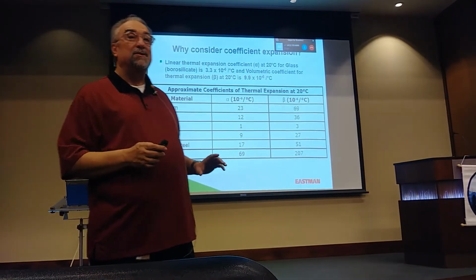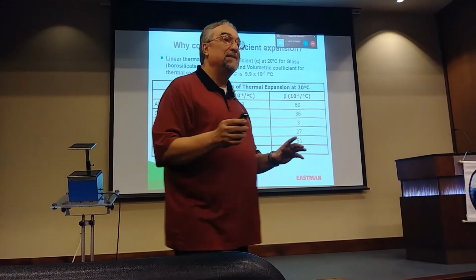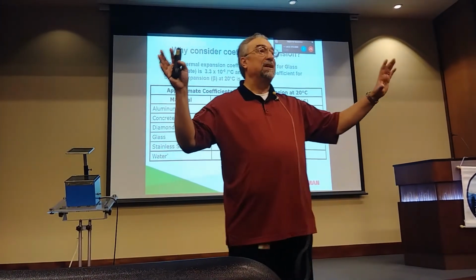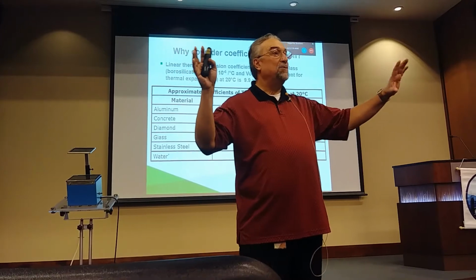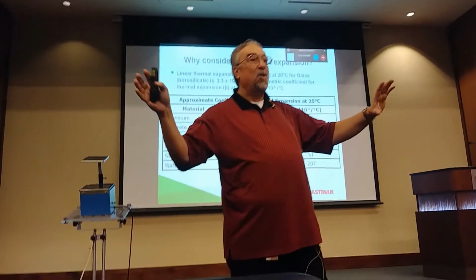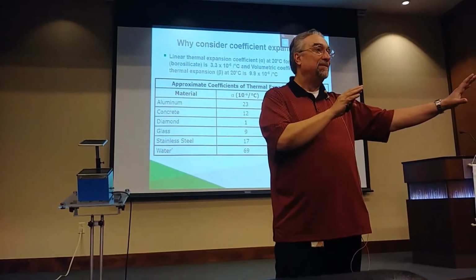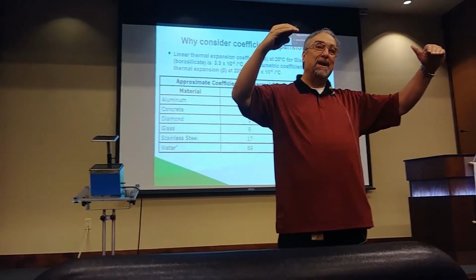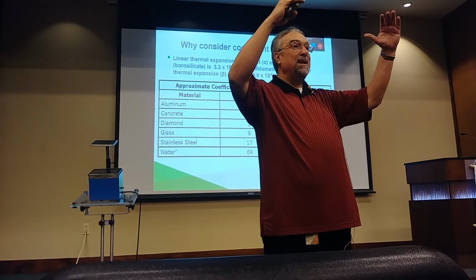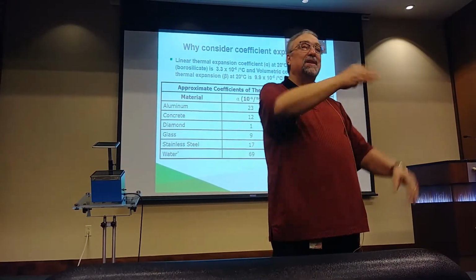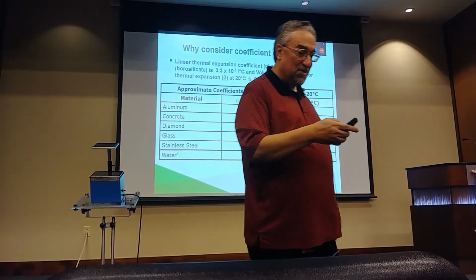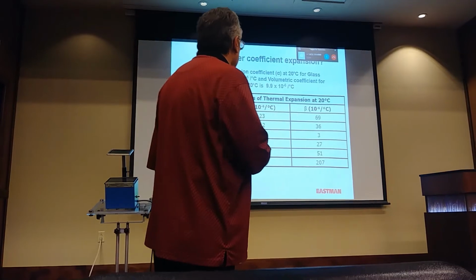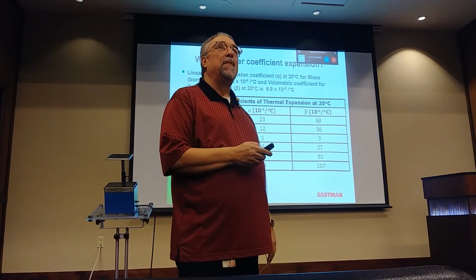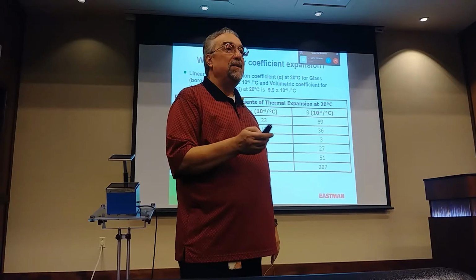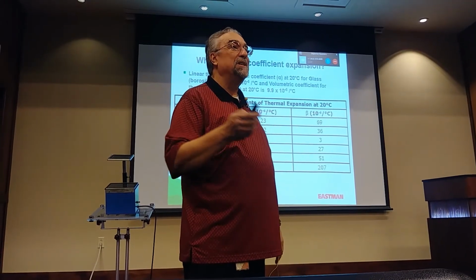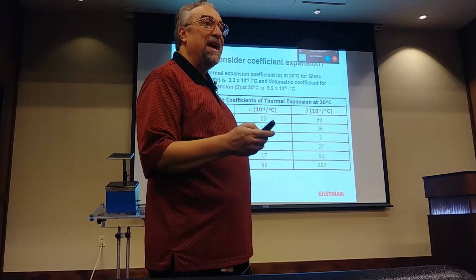There were some young engineers, I think I blame the engineering staff for this, and they made a big run of borosilicate pipe and forgot to account for the coefficient of expansion. And when they ran hot caustic through the pipe, it bowed up to the braces that were holding the pipe, and then another part of the pipe bowed down, so it looked like this. I had pictures of it for a long time, and I lost the pictures. But it was kind of cute because I think over a run of about 24 feet, you've got almost a 3-inch increase in length. So you have to take it into account if you're putting pipe together.